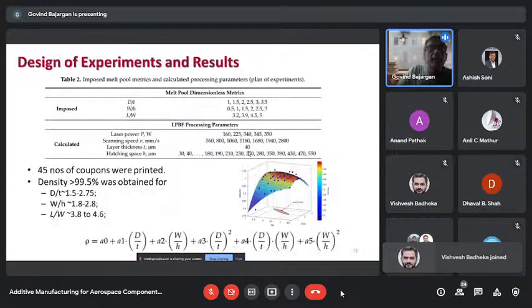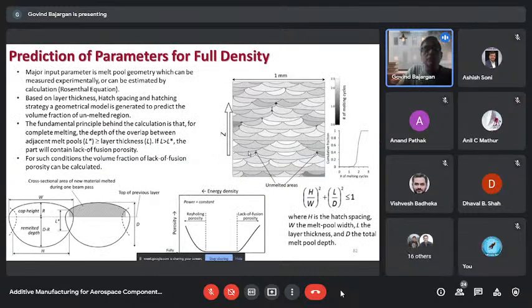So I'll come to one simplified model which people have used very innovatively. What people did is that they estimated the melt pool when the laser scans. This can be estimated experimentally, as well as with the Rosenthal equation. By writing simple code in Python and all, people have shown how the laser track will look when it is deposited, based on the estimation of melt pool dimensions. And then the next scan will be at 67 degrees. Then again the cross section of that is plotted using a Python program.